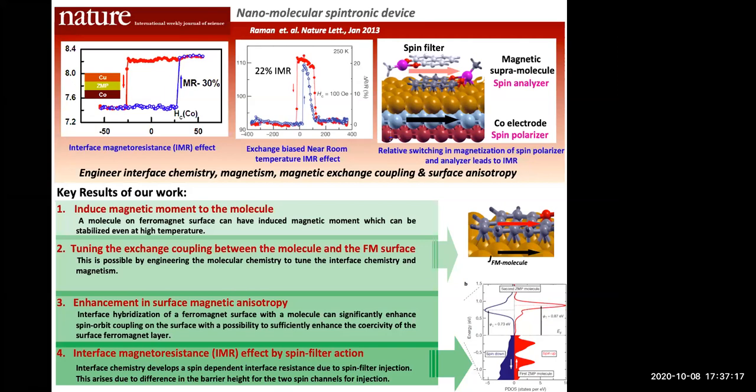So that effectively changes the interaction strength, the spin contrast across the interface, and effectively gives rise to different strength of hybridization. Okay. And if I may, I had a quick last question: how do you grow these molecules? Yeah, these molecules are stably thermally evaporated in an MBE system. So it's like an effusion cell kind of a thing? Yes, effusion cell, around 500, 600.